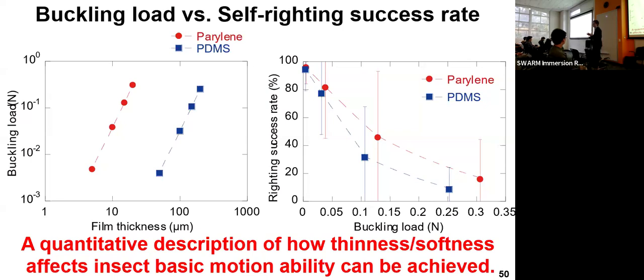0.1 Newton. And this is very good for applying these kinds of approaches to other soft robot actuator systems because many insects have similar segment movement systems. So if we consider similar soft robot systems, this can be fully applied. The important parameter should be the buckling load. Then, once we determine the threshold value, we can prepare the appropriate thinness or softness for the flexible devices. In these cases, 5-micron polyimide or transparent polyimide substrate films are enough.